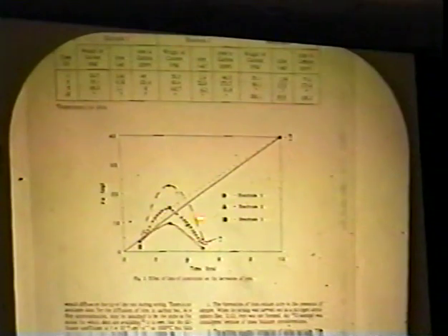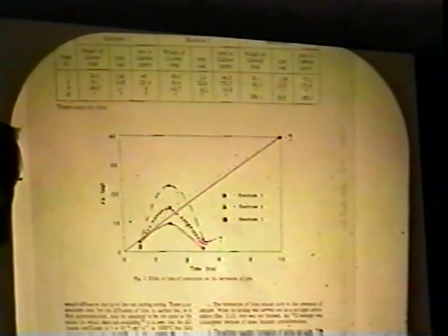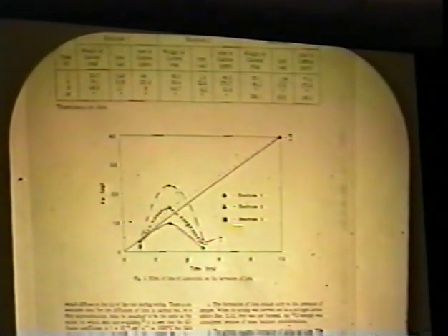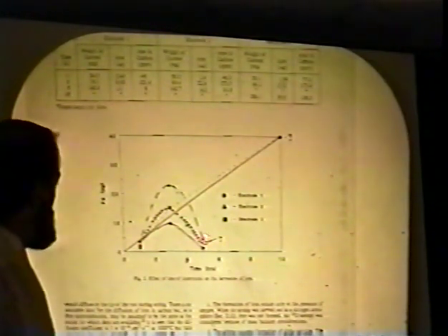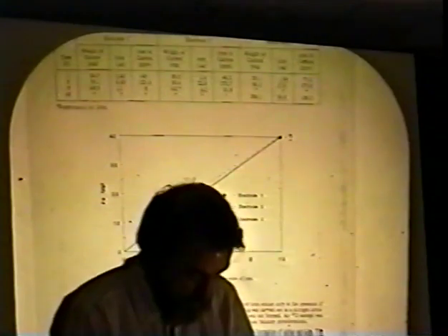The same with electrode number 2. At 1, 3, and 5 hours, they're getting to a point where they wouldn't get any more iron out of the sample. Possibly electrode 3, if you ignore this as a bad data point, you could say this experiment would also tend to fall along the first two sets of electrodes, reaching a point where you get no more iron out of the solution. That's just a possibility.